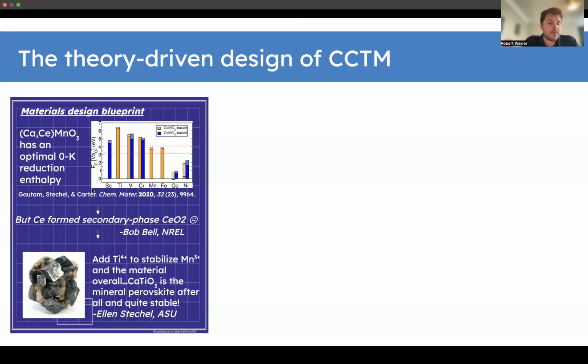So going with this, we collaborated with Bob Bell and Dave Ginley at NREL, and they tried to synthesize this material. But unfortunately, what they found was that upon synthesis, it wasn't single phase. It formed a ceria secondary phase, and upon reduction-oxidation cycling, that ceria phase actually grew in content. So unfortunately, the material couldn't withstand STCH conditions. However,